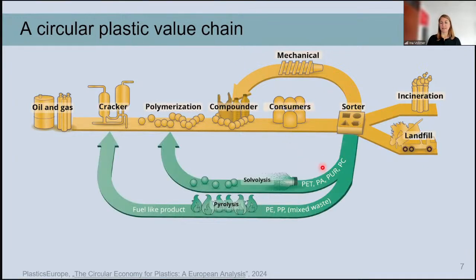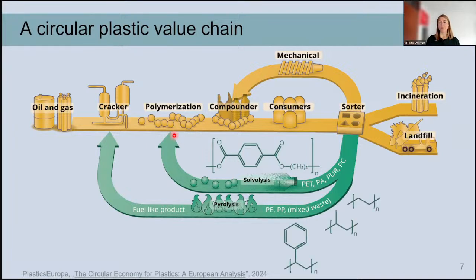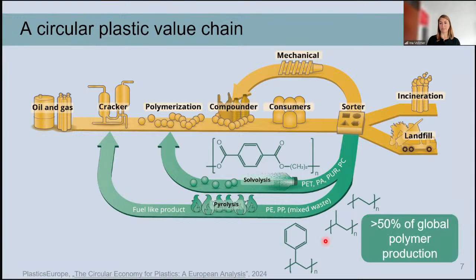So with polyethylene terephthalate, we can do solvolysis. And this yields back the monomers, so you can directly make a high quality polymer again. However, with polyolefins and also with polystyrene, you don't really have this weak link. So the only thing that you can do right now is provide a high temperature treatment and make a fuel-like product that has to be sent to the cracker again. And important here is that every step in this process requires a lot of energy. So ideally, we would find a process to make monomers out of polyethylene and polypropylene as well, because these make up more than 50% of the current polymer production globally.